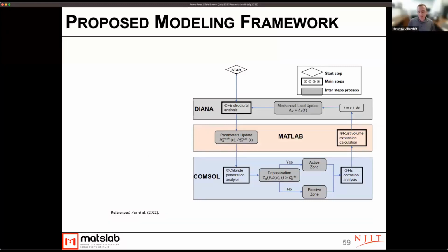We used a structural mechanics software that we use in our research group called Diana. It's similar to ANSYS or Abaqus or any other structural mechanics piece of software. The reason why we use it is because it has really good concrete mechanical material models that allow us to simulate damage quite nicely. Then, if we were to load something up and then wanted to simulate what the chloride penetration is at some particular time, we used MATLAB to connect our Diana software to a program called COMSOL. And this COMSOL software does multi-physics modeling that allows us to simulate the chloride ingress.